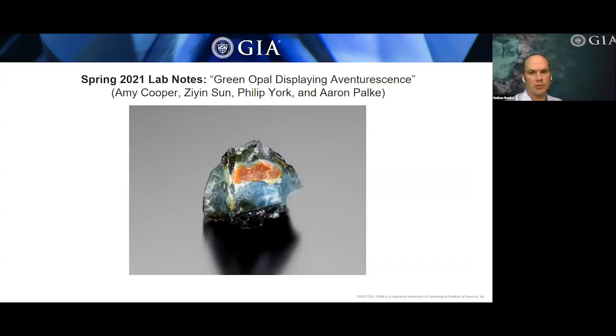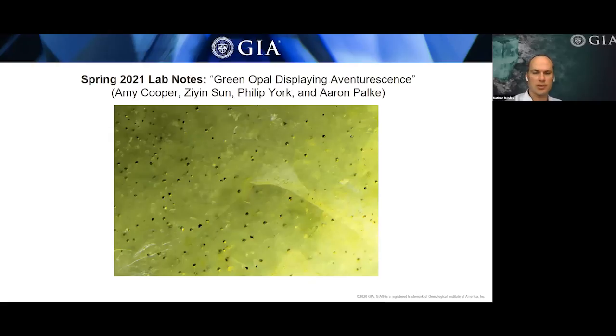In the Carlsbad laboratory, we were able to examine a unique type of green opal, and it was unique because it displayed some rather prominent aventurescence. If you look carefully, you see a glittery effect over this piece of rough. Unfortunately, it wasn't cut into a finished stone, but it was still quite interesting. In the microscope, we see that the source of the aventurescence was all these little metallic inclusions of pyrite that gave it this glittery effect. Pyrite is iron sulfide, which is consistent with the cause of color in this stone. So the cause of color in this opal was determined to be iron.